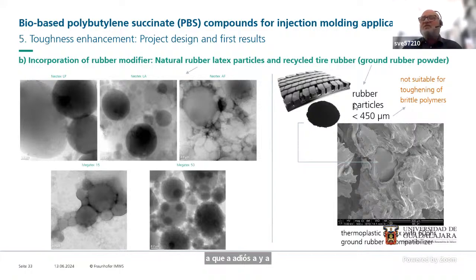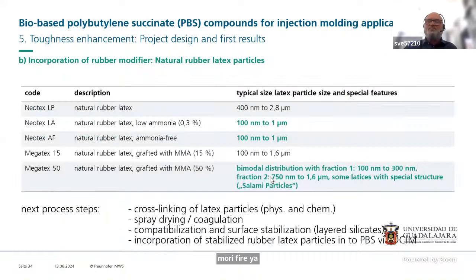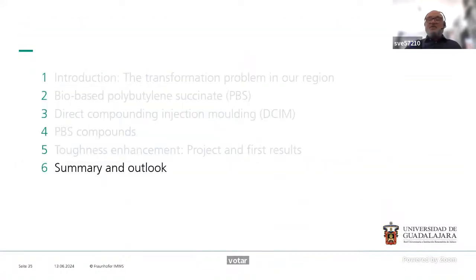The problem is that these rubber particles are still too big. They are not working as toughness modifiers. The particle size with 400 micrometers is just too big to introduce these favorable mechanisms. So we have to go the way here with the natural rubber spheres, the natural rubber cross-linked particles. That is what we have found. We have particles now produced in the range of 100 nanometers to 1 micrometer. What we expect is the optimum particle size for the toughening. And we have even found that there are some systems that are grafted with methyl methacrylate that have a bimodal particle size distribution that we can also try to get the optimum particle size, particle distribution, and interparticle distance. But that is exactly the status where we are at the moment. That is what we have to do in the next couple of months to get the product ready.